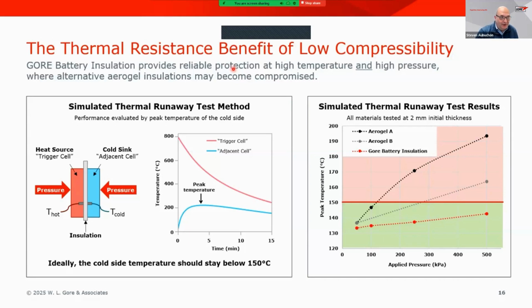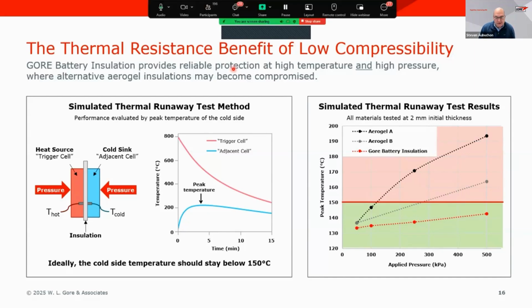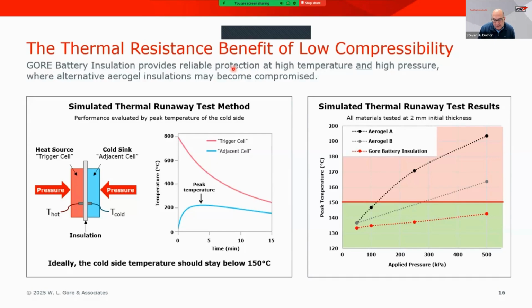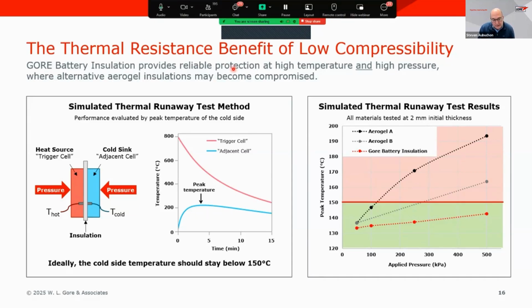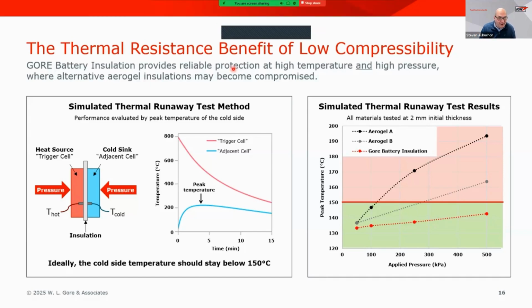So aerogels are remarkable materials. And to be clear, here at Gore, we are not anti-aerogel whatsoever. We do have some composite materials that do include aerogels, and we think they're fantastic materials for specific applications. We're a little concerned about using aerogels in the case of battery insulation, as I mentioned, because of the compressibility concerns that they bring. So, the aerogel materials are very light and they're very low thermal conductivity, but when they're deployed specifically to be battery insulation, they're often delivered in the form of a pad, and that pad has some sort of supportive scrim associated with it because aerogels are so light that it would be difficult to just sprinkle aerogel in between your battery cells.